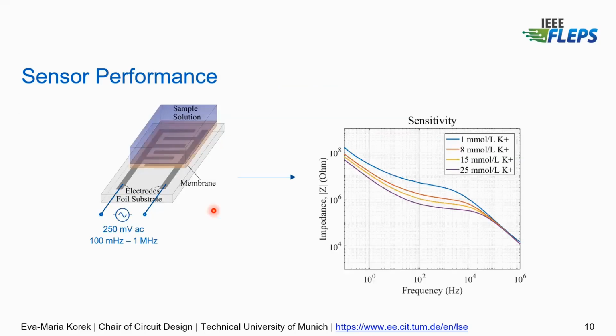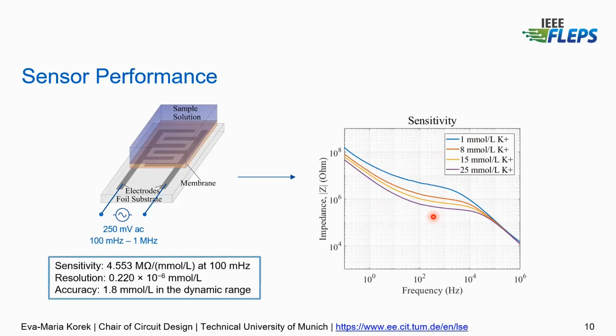Now, if we want to look at the sensor performance, we can see here we applied the frequency from 1 megahertz to 100 millihertz, and we can see with increasing ion concentration, the sensitivity of the impedance of the sensor decreased. At 100 millihertz, we actually achieved a good sensitivity, I would say. It's difficult to say because I cannot compare it because everybody else has potentiometric sensors and they use millivolts per ppm, for example. So we're using megaohm per millimolar per liter. The resolution is quite good, and the accuracy is okay, but I think for many applications, this accuracy is sufficient.